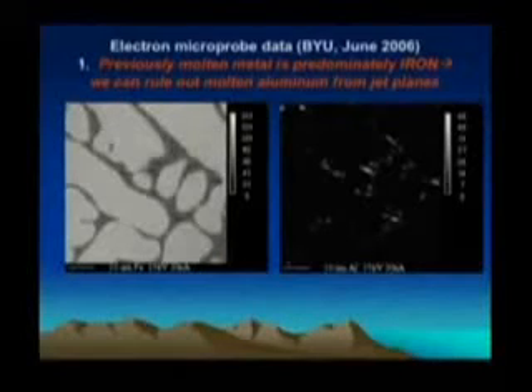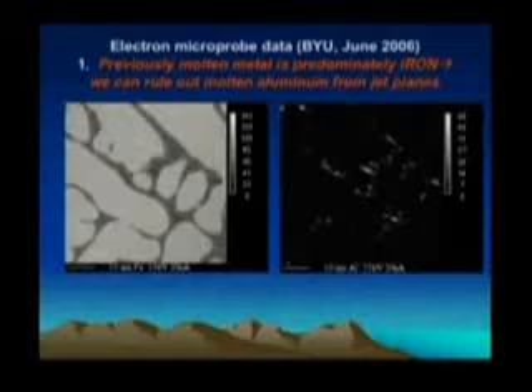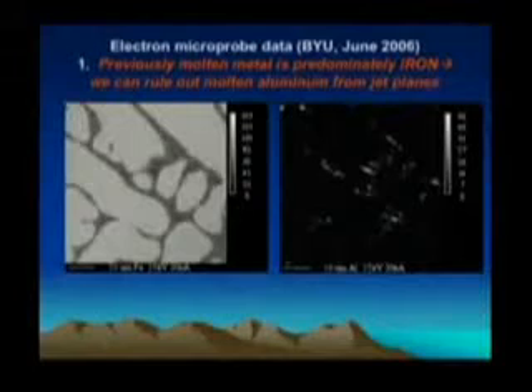On the left, we see abundant iron. Now the white means there's a lot of this metal, and the dark regions are where there is less of it. This is what you expect from a melt with other stuff in there. You expect regions of high concentration, which is the white bands, and then low concentration, which is the dark. And then on the right you see aluminum, but it's definitely there, but in spots. It's not mostly aluminum, it's mostly iron. We can strictly rule out molten aluminum from the planes in this material.